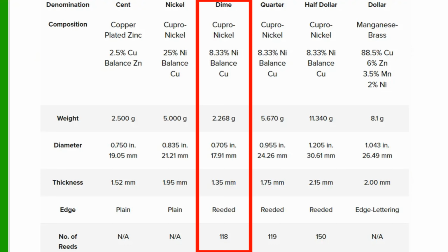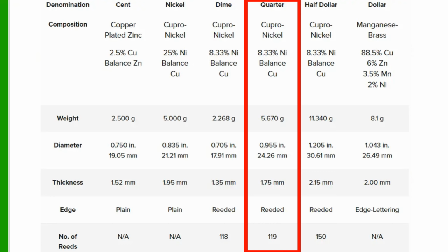The dime also utilizes copper-nickel alloy. However, the proportions are a little bit different: 8.33% nickel with the remaining being copper. It's lighter than the nickel, weighing only 2.268 grams, and has a small diameter of 17.91 millimeters with a thickness of 1.35 millimeters. Now, this is a little bit different, as this is the first coin of the three that actually has a reeded edge. Trivia piece for you: how many reeds are on that edge? Well, there's 118. The quarter shares the same cupronickel design as the dime, 8.33% nickel, balance copper, and weighs 5.67 grams, has a diameter of 24.26 millimeters and a thickness of 1.75 millimeters. Now, this also has a reeded edge, but this one has 119 reeds.